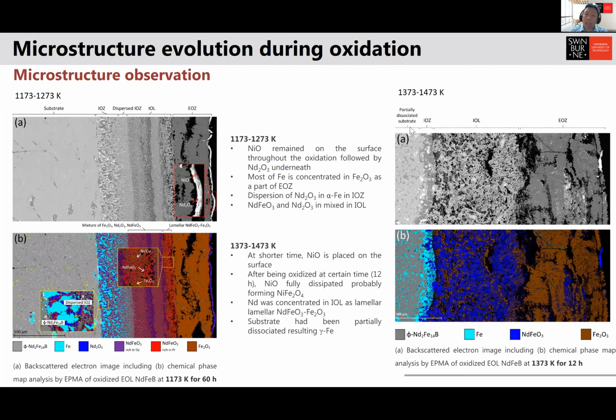So for example, on the right here, if we oxidize at 1373 and 1473, instead of having a lamellar, strip layer of NdFeO3 and Fe2O3, we have quite a blocky or sort of clumpy NdFeO3 phases here, right? So the one shown on the right, where you have this blue phases in there. So that's in a sense good, because it may be easier to separate these blue phases when you have something like this, compared to a quite thin layer of lamellar structure. So that's something that we analyze, or we observe.